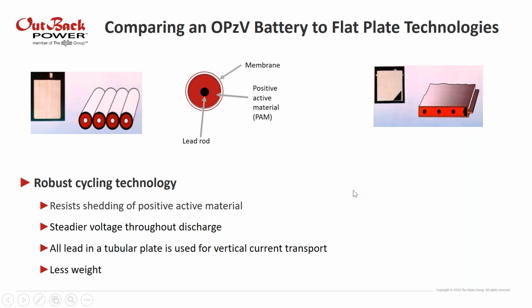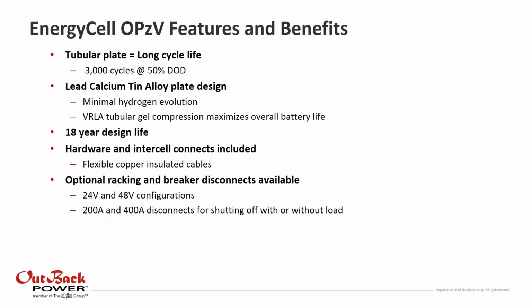And then another nice thing about tubular batteries is that if you were to compare a tubular battery to a similar grid pasted plate battery, the tubular battery would actually weigh just a hair less. So that's nice. Talking about features and benefits of the OPzV batteries, that tubular plate causes a really long cycle life. So you have 3,000 cycles at 50% depth of discharge. That's twice as many as a typical RE battery, for instance. So that was 1,800 at 50% depth of discharge. This is 3,000 cycles. It is a lead calcium tin alloy design, so that minimizes that hydrogen evolution, again, just increasing your charge efficiency. Rather than using energy to make hydrogen, you're using energy to charge a battery.